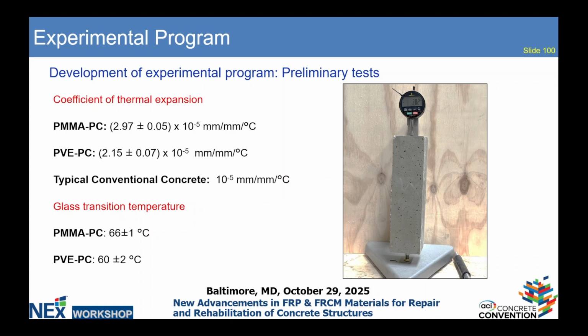We measured the coefficient of thermal expansion, as shown on the right, with a comparator at different temperatures. We used 23 degrees Celsius to 100 degrees Celsius as the temperature range, and found that polymethyl methacrylate polymer concrete has a coefficient of thermal expansion of around 3 × 10^-5 millimeter per degree Celsius, and polyvinyl ester had 2.15 × 10^-5 millimeter per degree Celsius.